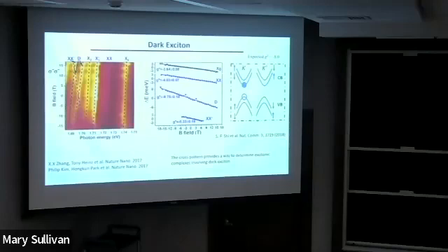So that's why the oscillator strength is small to start with, so the PL signal is not huge. In addition, the light is actually coming out from the side, so you cannot see it easily. But this dipole, the maximum is here, but it's a cosine-squared dependence, so it's not a dramatic change. If your collection angle is large enough, you're going to collect a finite amount of this light anyway. So what we did is we used a fairly large NA, roughly 0.5 to 0.6. That's enough to collect enough signal from the side. So that's why you see it here.